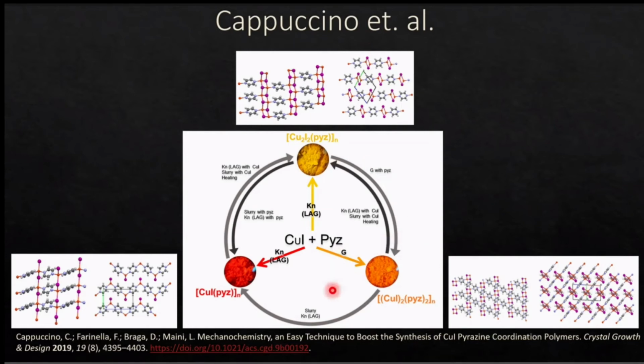So we looked at this and we saw, okay, the orange is spontaneously decaying into the red, and for the red and the orange both, you have to add energy to get up to the yellow. And so that means that the yellow is of the highest energy, orange is lower than yellow, and orange is higher than red. And so you can go through that process and start to look at how these are related.